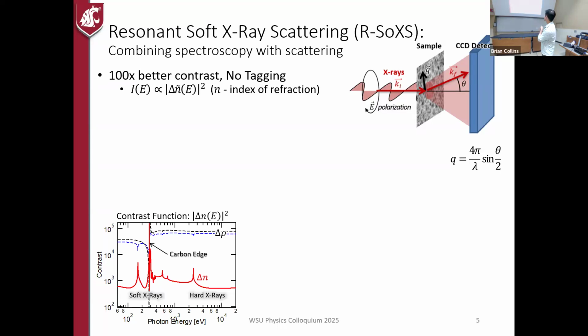What's really interesting here is that the intensity of the pattern that encodes the structure is sensitive to the difference in the index of refraction between different locations on our film. So if you have more difference, then you're going to get a bigger signal that you can be sensitive to more subtle things. And so we call that the contrast function.